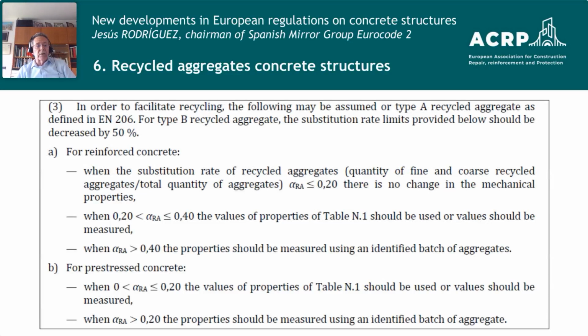we can maintain the conventional approach of concrete without recycled material. In the case of an amount between 20 and 40%, there is some information in this annex on how the conventional values are to be reduced. And finally, with more than 40% recycled material, we need to test and verify the properties through testing. In the case of pre-stressed concrete, the amount is reduced.